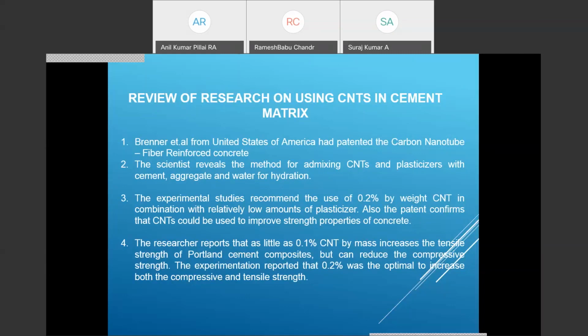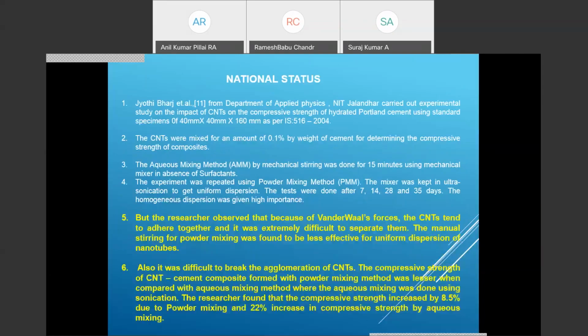matrix. At the national level, there are various institutions including NIT Jalandhar using carbon nanotubes in their research, but most of the researchers use the powder mixing method and ultrasonication for mixing carbon nanotubes with the concrete or cement. Because of agglomeration, the carbon nanotubes get clogged together. To avoid this, you can use surfactants. The compressive strength has been improved by 8.5% due to powder mixing, and a 22% increase in compressive strength by the aqueous mixing method has been observed.